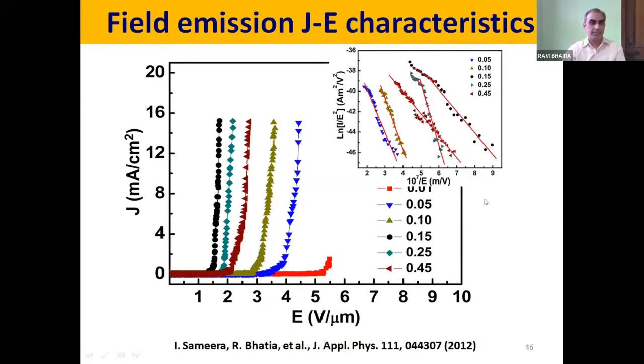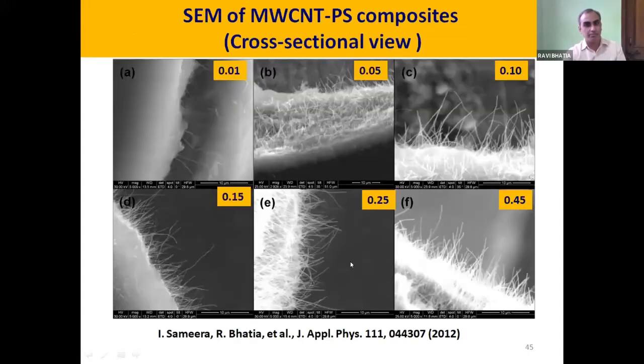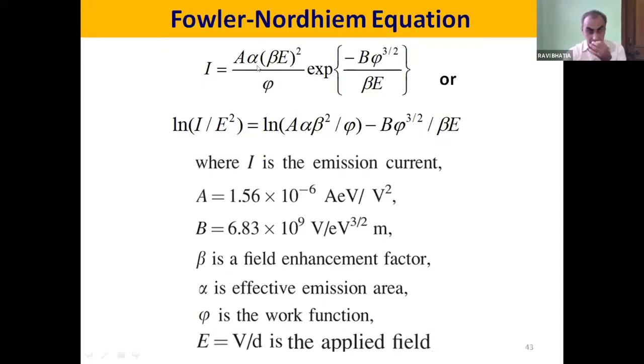So this is a very interesting curve. One can look at it. Before that, I will again go to this particular equation, the Fowler-Nordheim equation. I by E square. I is obviously the current, the emission current. E is the applied voltage, and phi is the work function of the material. Generally, we take it as 5.0 electron volt as that of graphite, because just to study field emission, we consider that the multi-wall carbon nanotubes are equivalent to graphite.